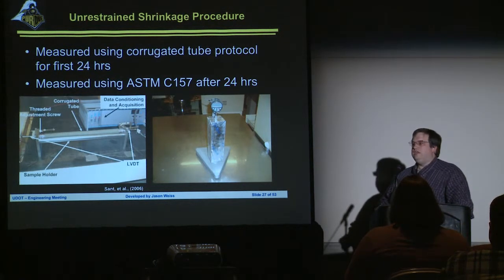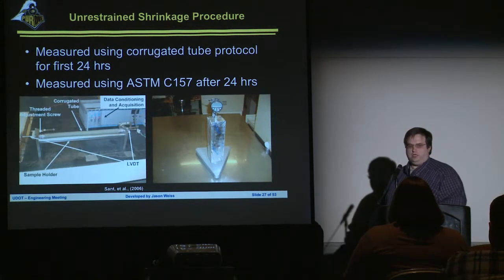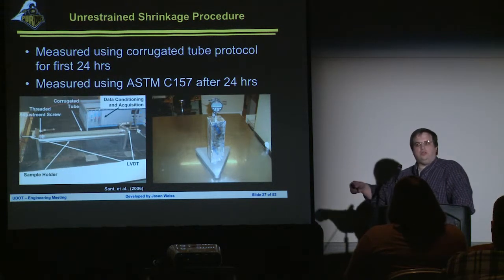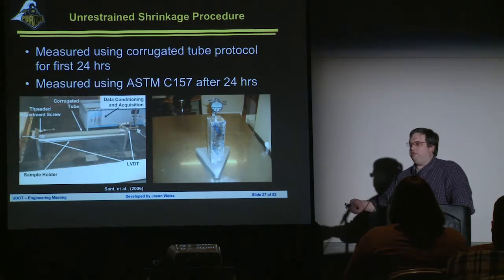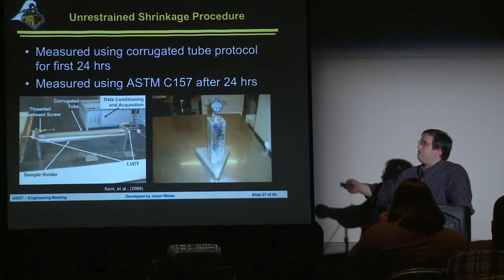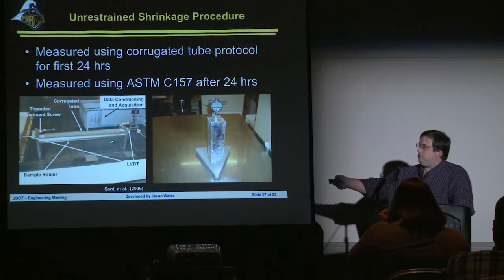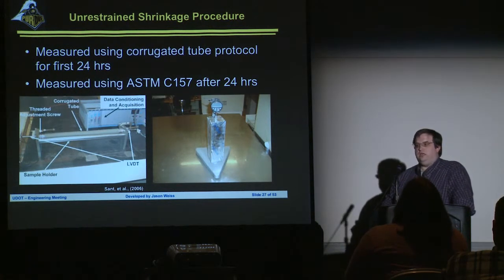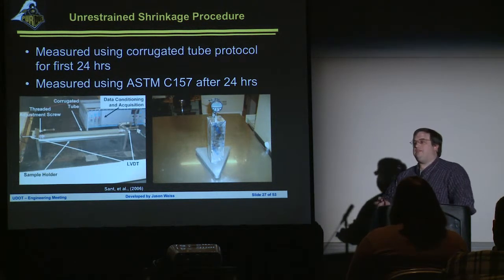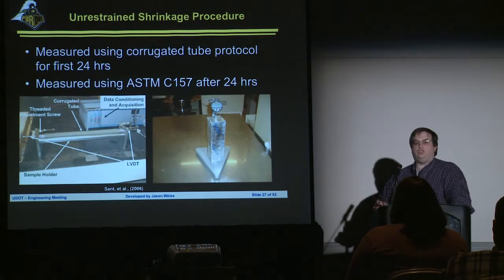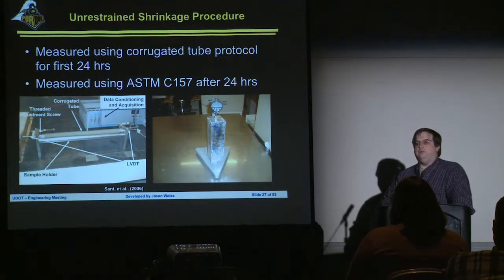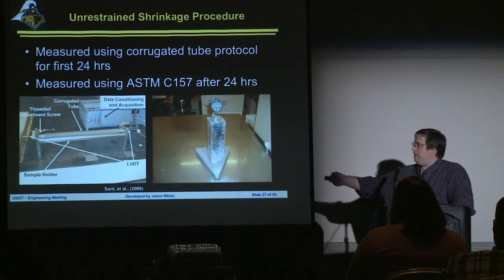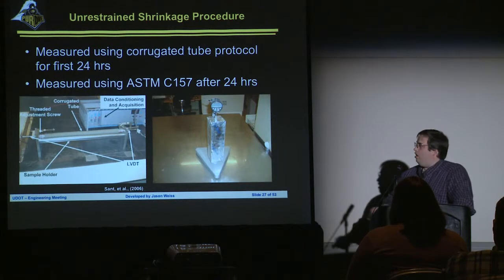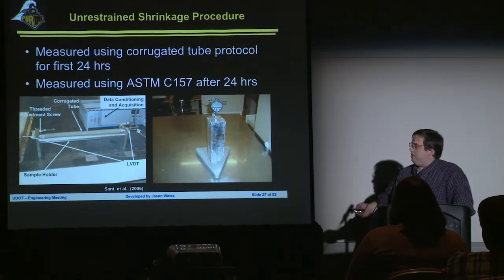Because our conventional tests essentially say wait 24 hours and then start measuring shrinkage. How did our concrete know that it should start shrinking at 24 hours? As we saw earlier, shrinkage really starts from the time the water and cement come in contact with each other and becomes a real big problem once the system starts to set. So what we've essentially done here is we've been working with a test procedure that's like a big crinkle cut French fry. This is an accordion type of tube which has very high stiffness in the radial direction, almost no stiffness in the longitudinal direction, so you can measure length change from the time the concrete is fluid. You can zero this at the time of set and you can start to measure these length changes very early on. Right?